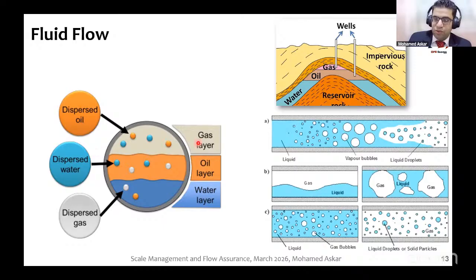What about gas? I told you at the beginning that this gas may have some H2S, hydrogen sulfide, and carbon dioxide, CO2, which are sour gases. The sour gases, when dissolved inside the water, make carbonic acid, and this acid can dissolve or interact with the metallic parts. There is also a phenomenon called sulfide stress corrosion cracking, where H2S can cause damage and corrosion to the pipeline itself, to the metallic parts, especially the compression equipment and the turbines, due to the high pressure. So all these fluids can cause flow assurance issues and challenges that I should care about and prevent from happening. Do you have any questions till now, or is everything clear for you?